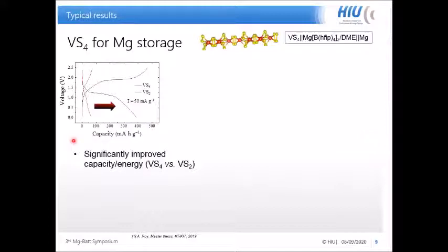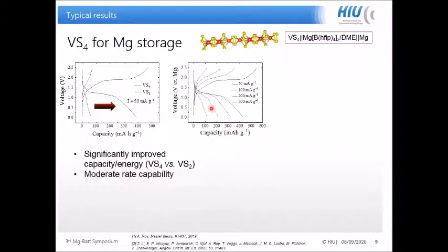Then we studied the magnesium storage in this VS4 cathode. This is a typical discharge and charge voltage profile. We also compared with the VS2 cathode, which was prepared using a similar hydrothermal approach. It is very clear that we have much more prominent discharge plateaus and a significant increase in capacity. The VS4-based cell we also ran at different current rates, even at a current of 500 milliampere per gram with moderate capacity retention.